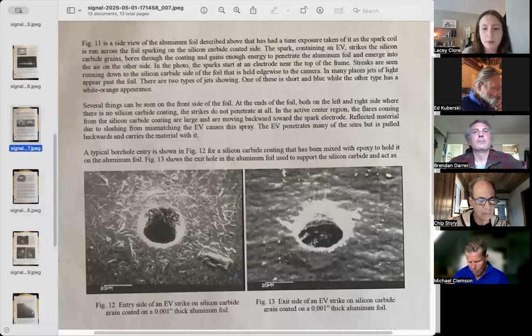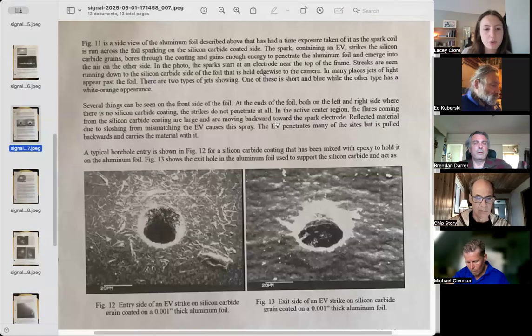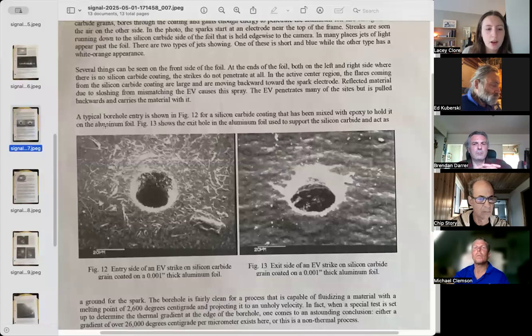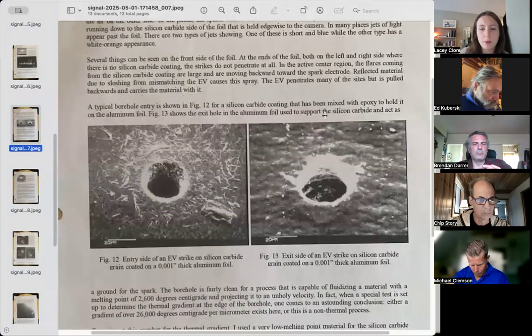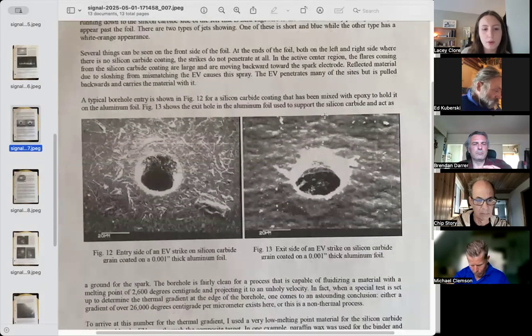In the active center region, the flares coming from the silicon carbide coating are large and are moving backward toward the spark electrode. Reflected material due to sloshing from mismatching the EV causes this spray. The EV penetrates many of the sites but is pulled backwards and carries the material with it. A typical borehole entry is shown in Figure 12 for a silicon carbide coating that has been mixed with epoxy to hold it on the aluminum foil.